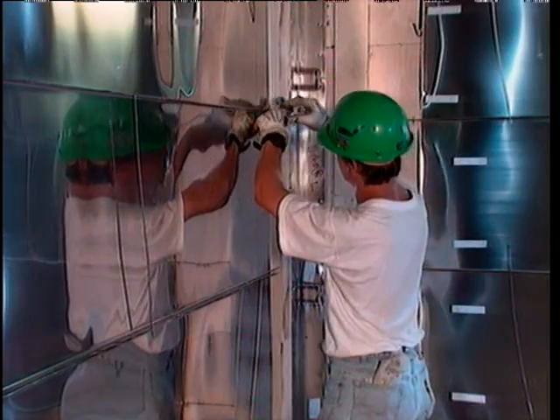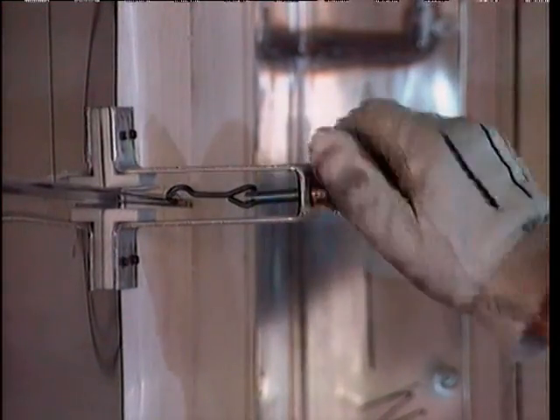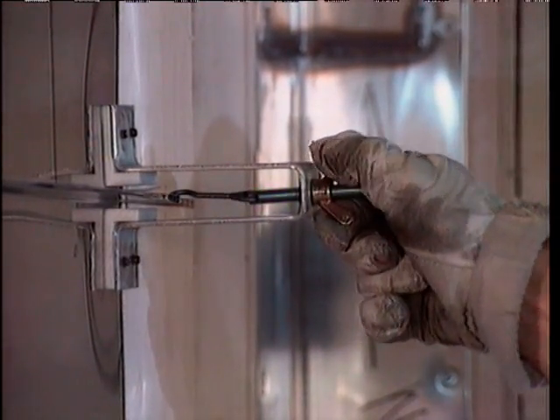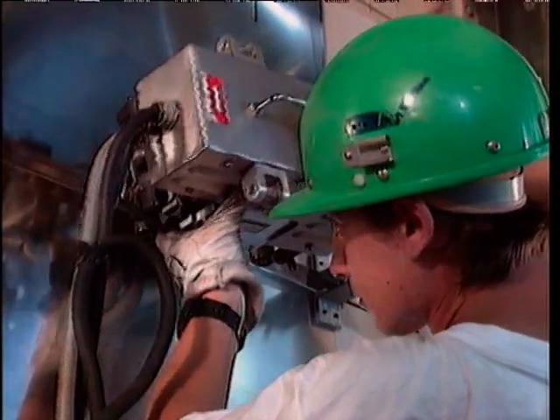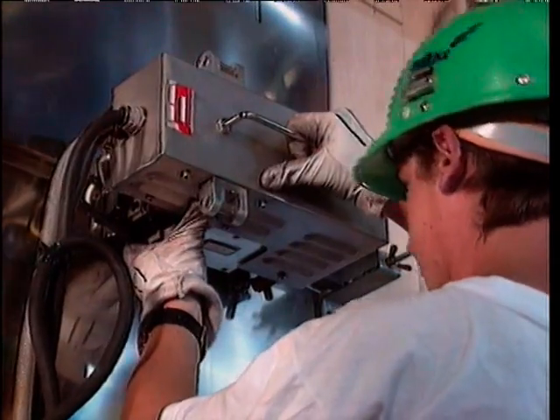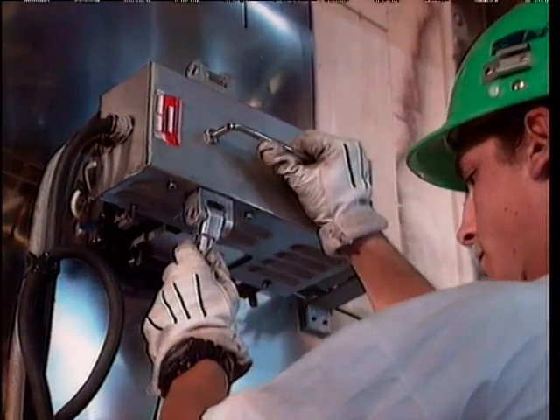The strakes are held in place along the wall by means of temporary devices consisting of a hook anchored in the eyelets cut in the tongue. The strakes are then flanged into position by tack welding onto two adjacent raised edges on the intermediary tongue. This operation is carried out using a light automatic resistance welding robot.